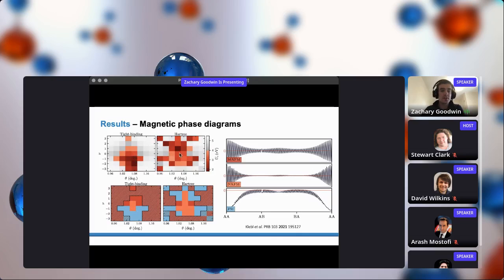Whereas with these Hartree interactions, we have magnetic order over a wider range of twist angles and doping levels, because these long-range electron interactions are inducing band flattening in addition to the twist angle. And so we can also extract what magnetic order occurs at each twist angle and doping level. And I'm showing that in the lower two panels.